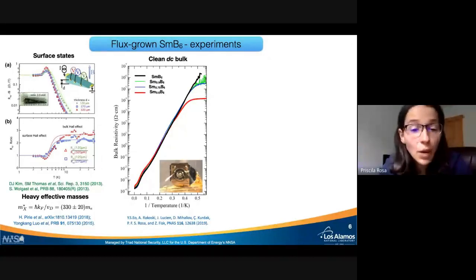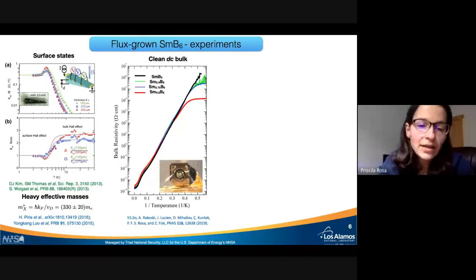So here's the bulk resistivity of samarium B6 versus 1 over temperature. This is the so-called Arrhenius plot. And you will notice that we don't have the saturation below 4 Kelvin anymore for the pure samarium B6 sample. This is the black line. And it's quite remarkable that the bulk resistivity rises by 10 orders of magnitude on cooling.